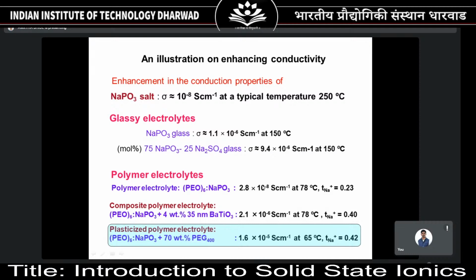Then you made a composite electrolyte. Further, you could get 2 orders of enhancement in the conductivity and see that the transport number also enhanced. And when you had a plasticized electrolyte, the conductivity further increased. Though the temperature is lower, the conductivity looks like 10 to the power -5 at a much lower temperature, and the transport number also increased to 0.42. And with this, I will conclude my lecture explaining different kinds of possible electrolytes: crystalline, glassy, that is amorphous, semi-crystalline materials, and composites, and how one can tailor-make or enhance the conductivity of a typical material.